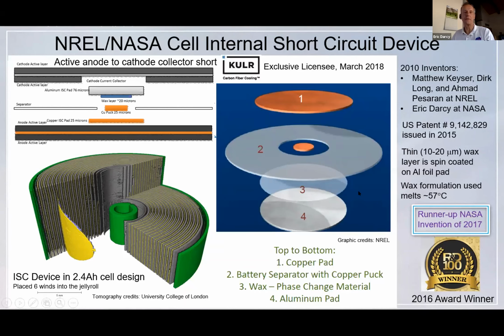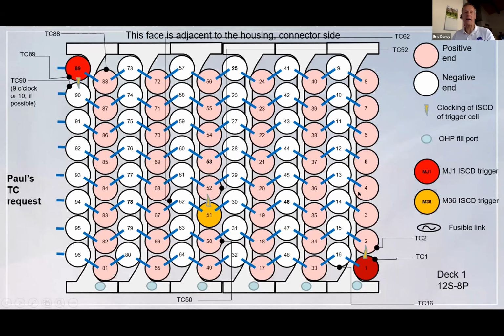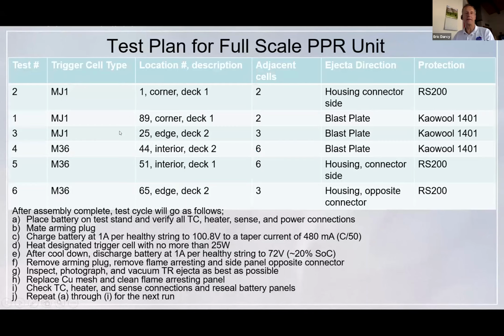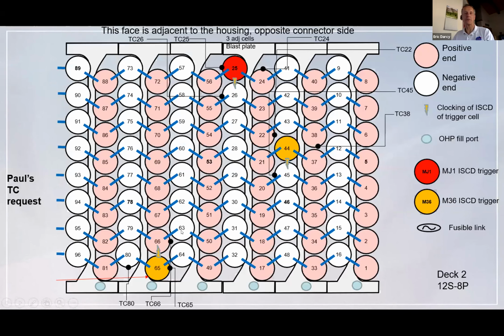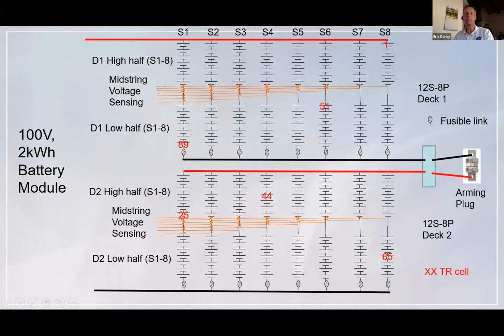Makes it a lot easier to trigger thermal runaway with a lot less biasing of the adjacent cells. So we built these decks with these trigger cells in these locations here that I'm showing. So we had a mixture of corner cells, interior cells, and also some edge cells, as I'm showing over here. So we had 6 total trigger cells in our test campaign.